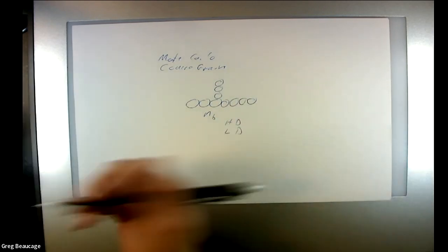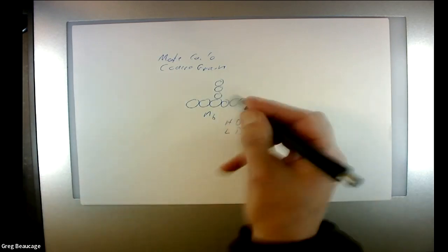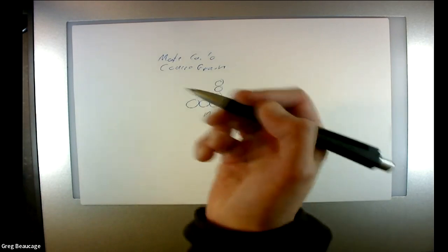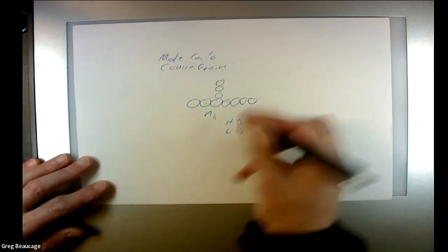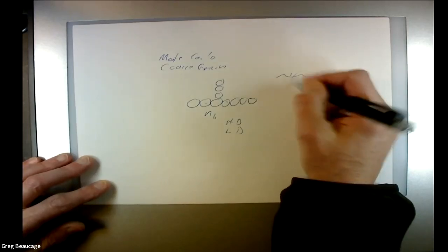This is like polyethylene, because you can put in a copolymer that has a butene comonomer. Instead of ethylene, it's got an ethyl group on the side, and that causes the chain to have these defects so that it'll crystallize only to that thickness, more or less. And so you can reduce the crystallinity and control the crystal size, which controls the melting point.